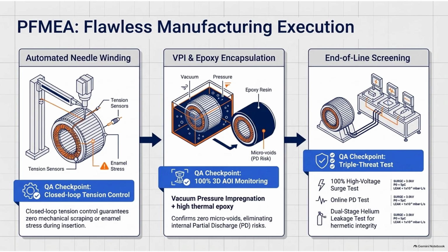But they don't stop there. We move to the inline testing. Before the motor ever leaves the assembly line, they hit it with a 100% surge test. What are they looking for with a surge test? They fire high-voltage pulses directly into the coils to create an LC resonant circuit, and they analyze the electromagnetic waveform decay signature. If there is even a microscopic turn-to-turn short the optical inspection couldn't see, the resonant frequency and the damping of the waveform will degrade slightly compared to a master signature. So they compare it to a perfect model. Right. The automated machine catches the deviation and scraps the motor.